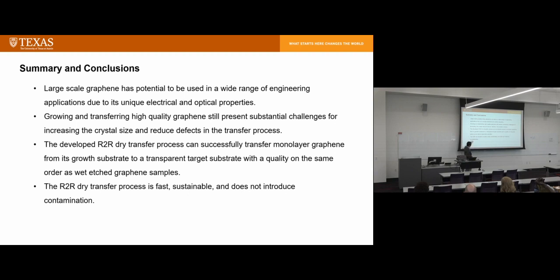The process we developed can be used to transfer large-scale graphene, although the quality, the surface resistance, right now we quantified surface resistance, is still in the kilo-ohm range, but it's on the same order as wet transfer graphene. And dry transfer graphene has a lot of advantages, including there's no chemical contamination, the process is fast, and you can recycle the graphene growth substrate, so that's a big benefit also.